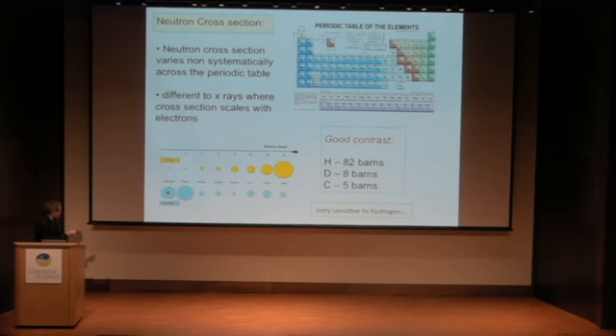A very interesting aspect with neutrons is that one of the largest cross-sections is associated with hydrogen. I illustrate that over here. This is the cross-section for hydrogen, deuterium, which I'll come back to, and also carbon. You can see that the hydrogen cross-section completely dominates, which makes neutrons very sensitive to hydrogen. Usually, as neutron scatterers, we try to get rid of hydrogen because it's such a strong scatterer, so we avoid things like glue. But you can use it to your advantage and study molecules that contain hydrogen.